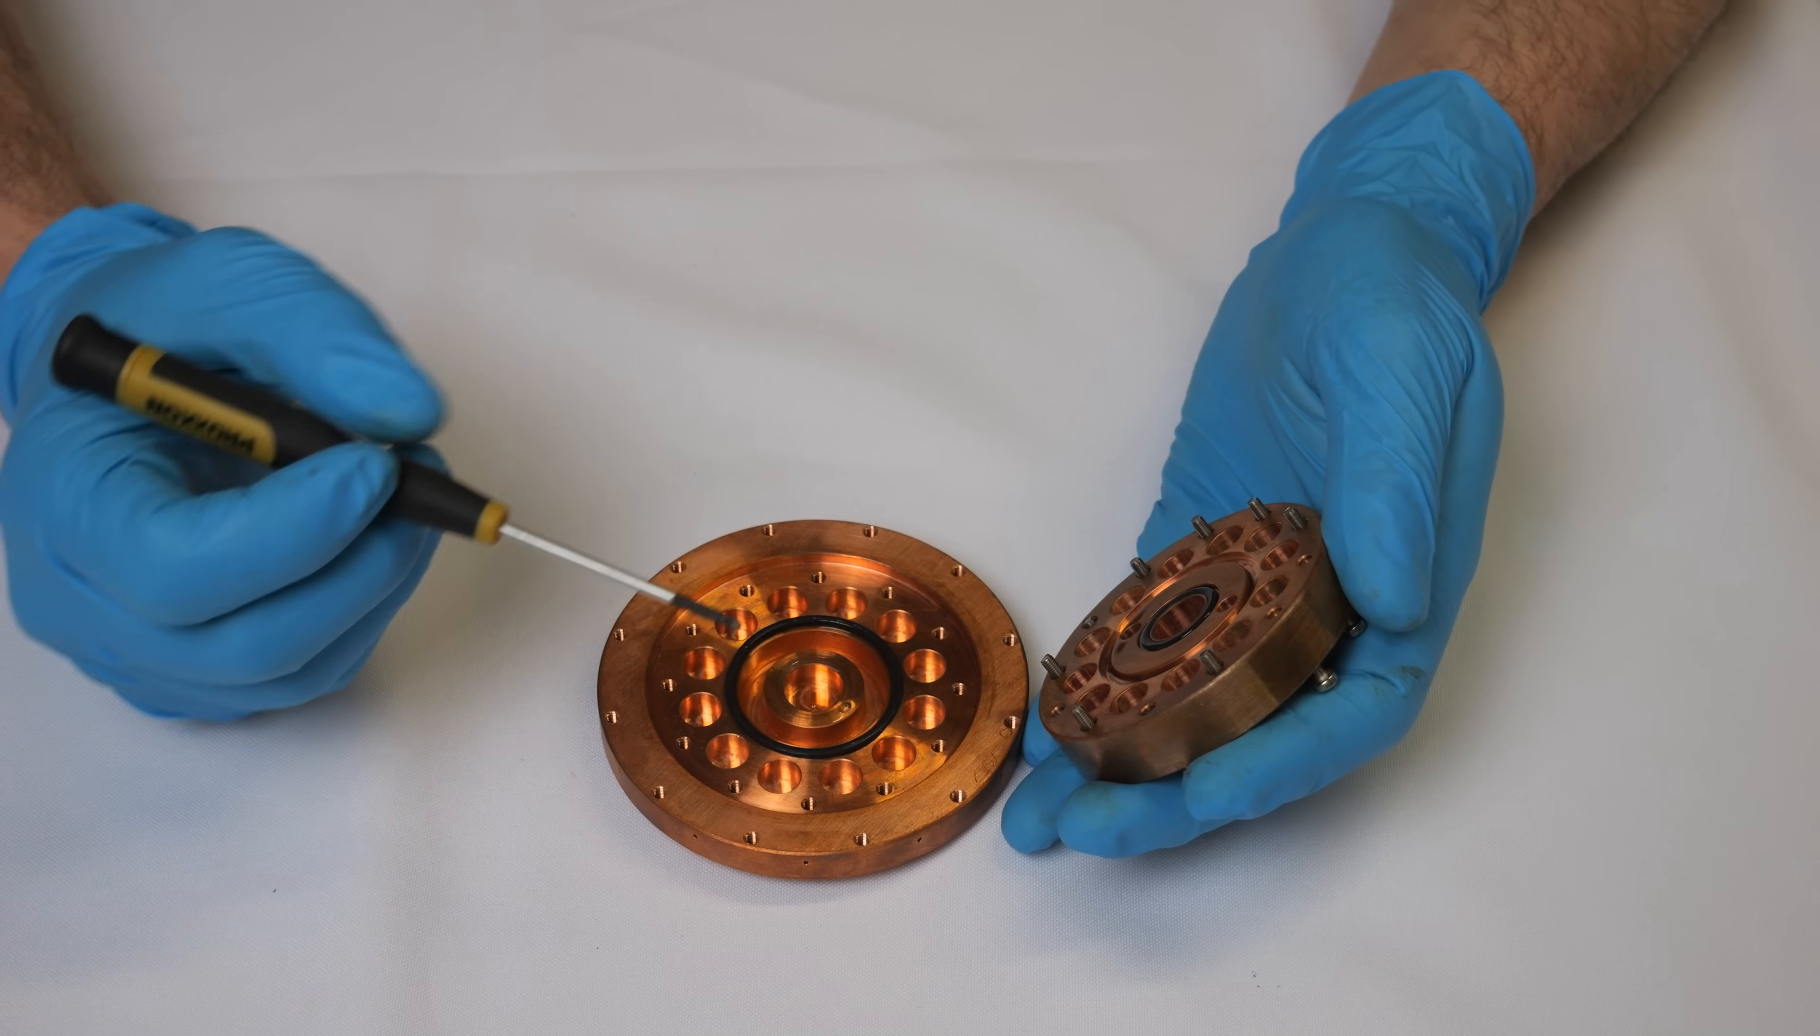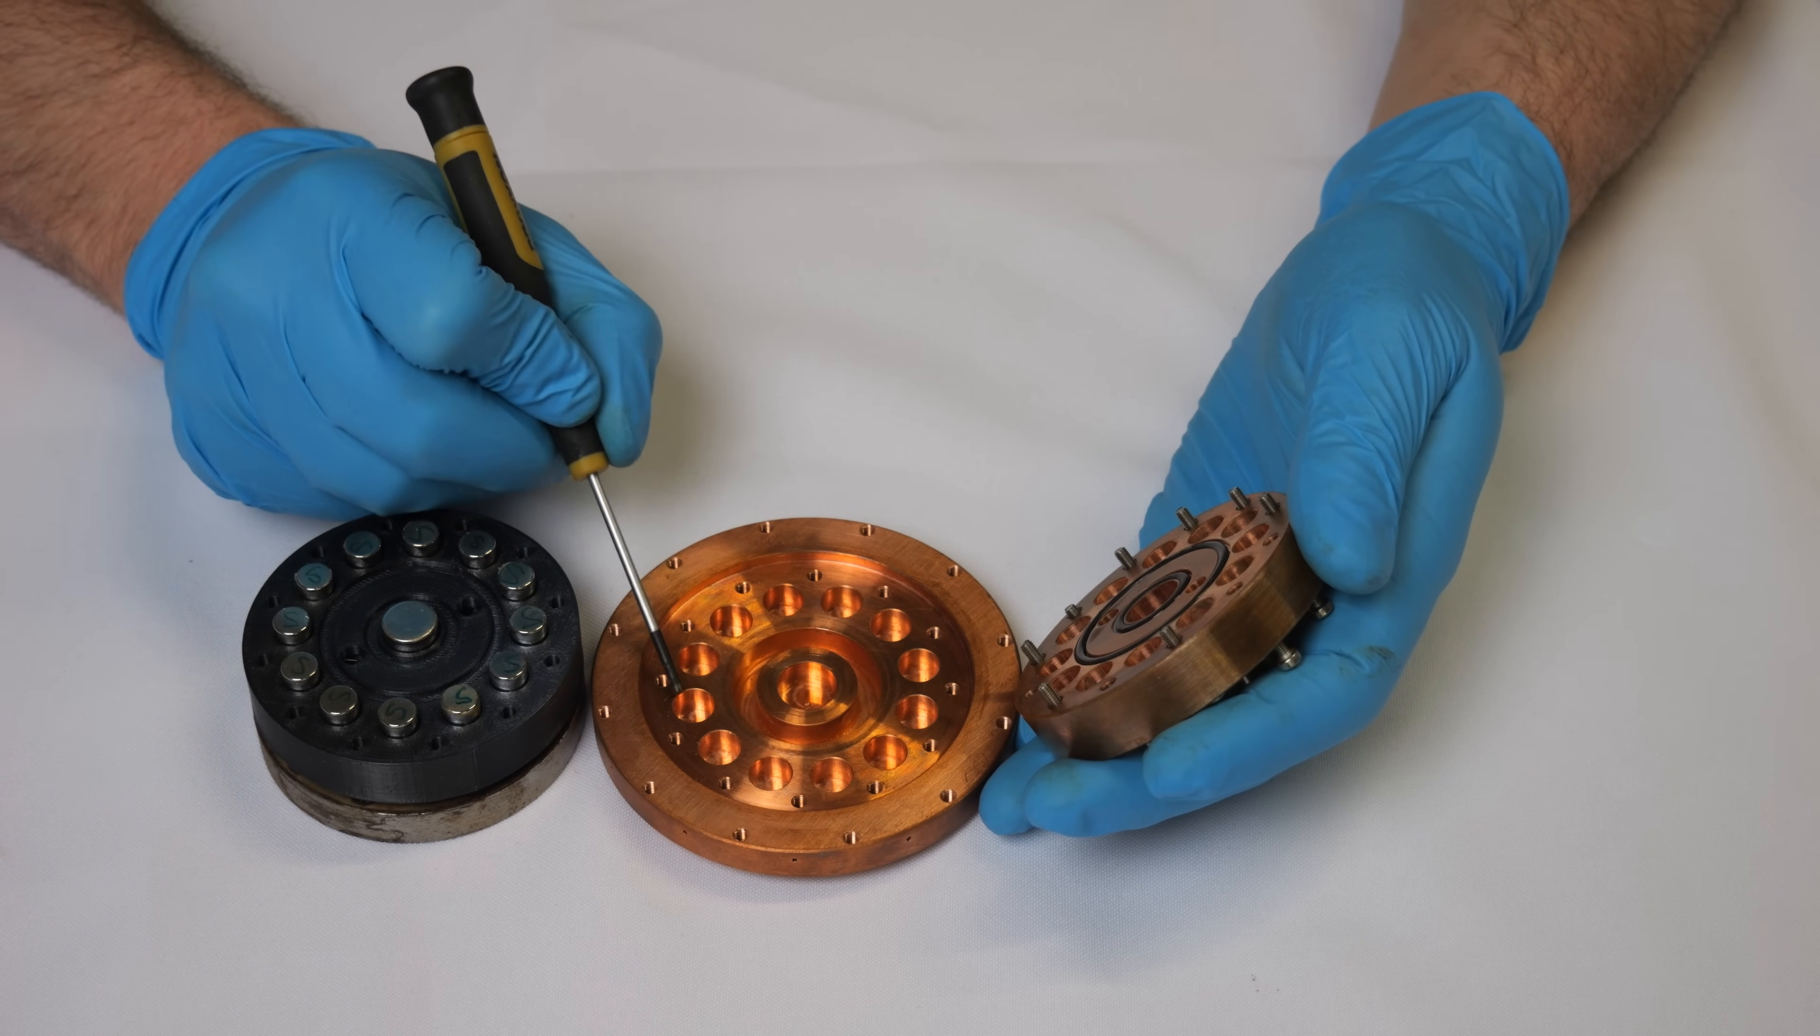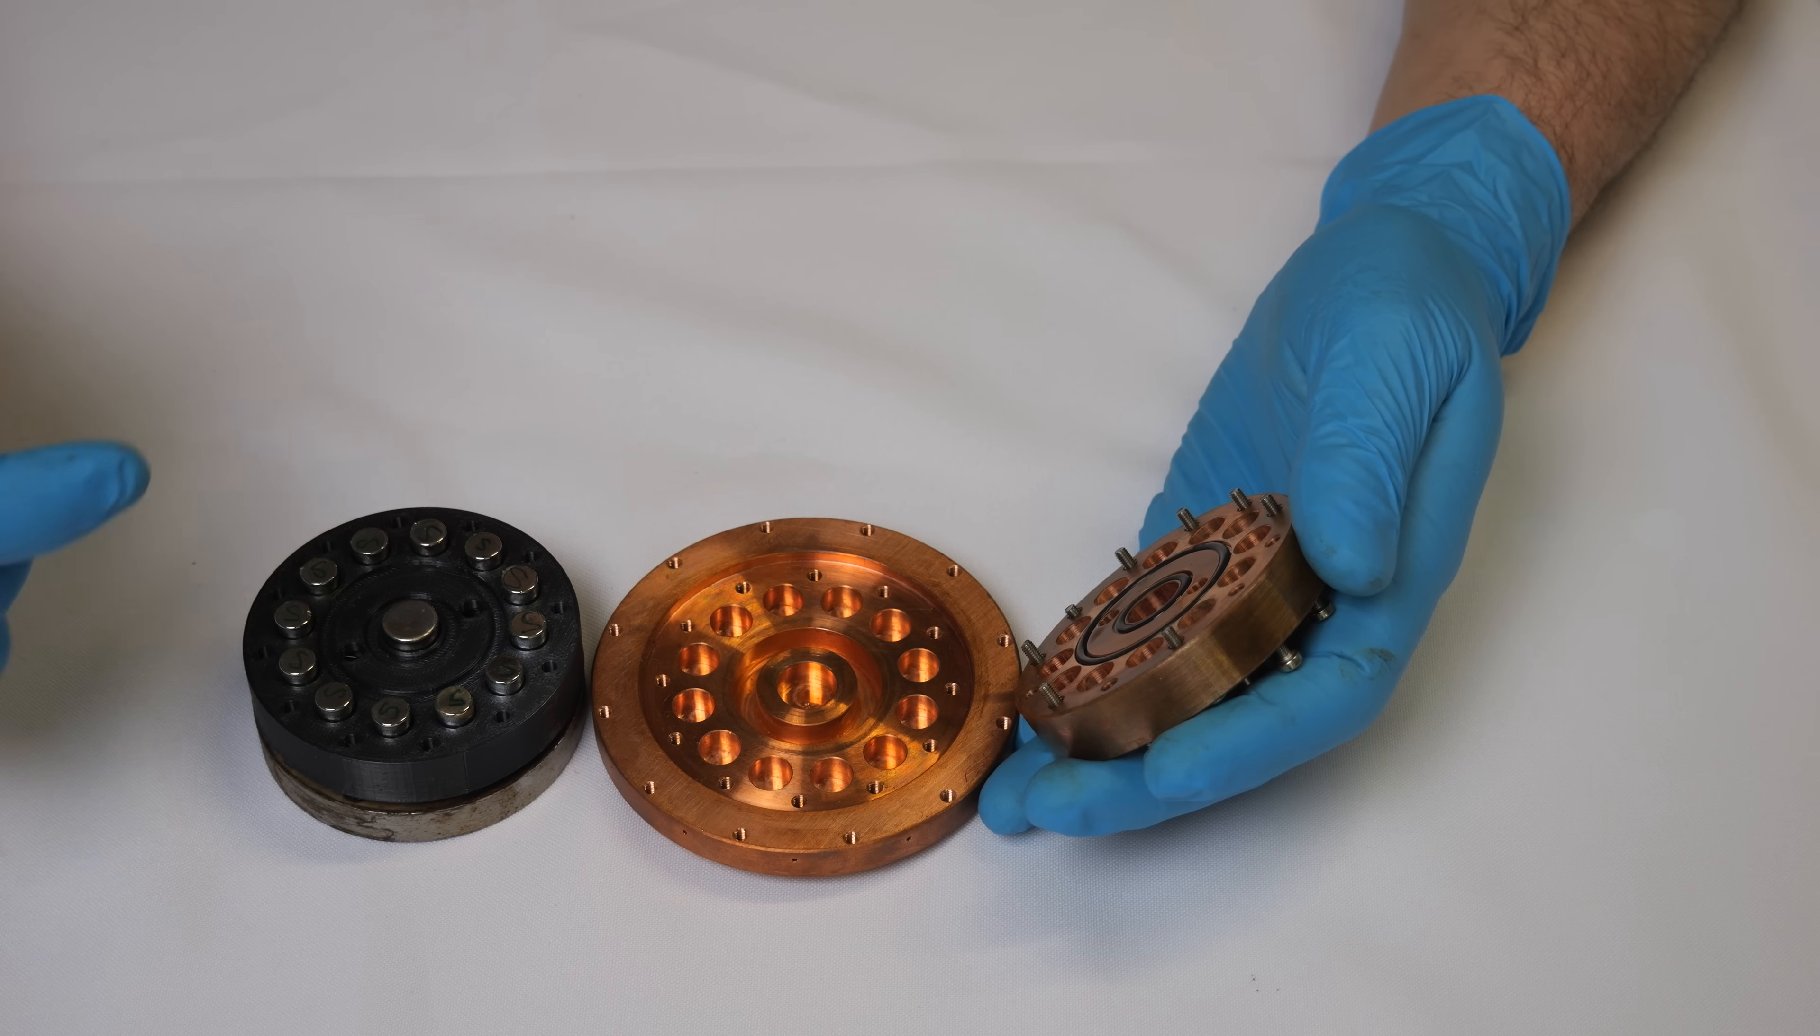Here is basically the last important part which is the water cooling channel. An important design consideration you can see right here is that the water cooling channel is completely separated from the magnets. That's crucial because these magnets here will, even though they are coated, easily erode when in contact with water and the copper. I also wasn't aware of that fact when I designed my first version of this magnetron. But the member of the AGS in Braunschweig made me aware that you basically have to scrape your magnets out of your magnetron if they are in contact with the cooling water.